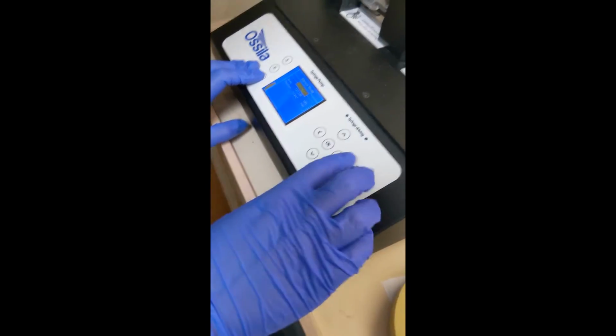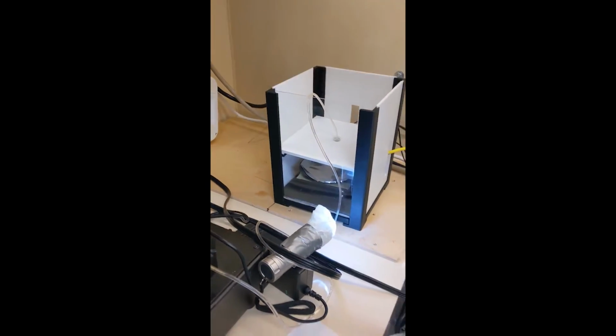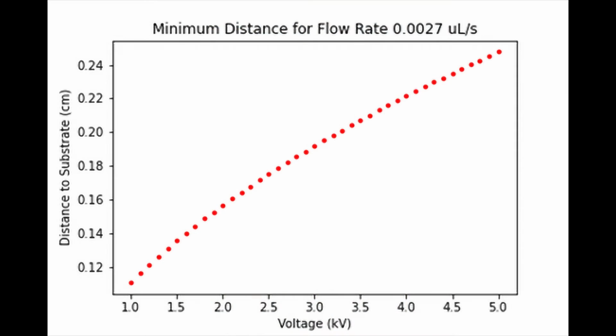This deposition system has been modeled to ensure that all solution is evaporated by the time the nanoparticles hit the surface. In order to have all the solution evaporated, the distance and voltage must fall within a modeled range, and a Taylor cone must be formed to ensure all droplets are charged. Taylor cone formation is ensured through a computer vision system which uses edge detection to calculate the semi-vertical angle of the cone to ensure that throughout the deposition process the Taylor cone is maintained.